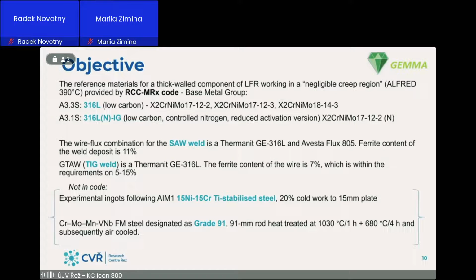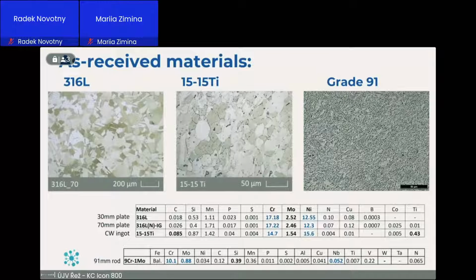Our goal was to test some reference materials from the RCC-MRx code that were chosen for the Alfred reactor for thick-walled components. And it was 316L and 316L low nitrogen, and submerged arc weld and TIG welds, and also 15-15 titanium that was 20% cold worked and experimentally made, and we also tested grade 91. So these are the materials in the as-received state. 316L was solution annealed. In 15-15 titanium, you can see some slip bands from cold working and big grains.